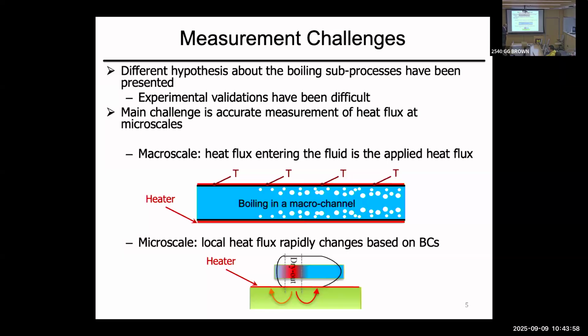But once you go to the micro scale, and you're trying to understand this phenomenon, let's say a bubble is forming on the surface and moving, even if you apply constant heat flux at the surface, it doesn't mean that the heat flux is constant. Heat flux is changing within the solid in microseconds and milliseconds. Because let's say you have a bubble and all of a sudden thin film formation here, evaporated now. So this is insulated now. So heat will start going from the heater to this location where you have an extended meniscus, and you get much, much higher heat transfer.